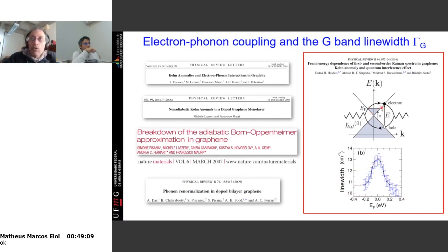Why? Because when you dope the material, you take this level and put it up here. But if you fill the electronic structure up to here, you cannot generate this transition anymore, because of the Pauli exclusion principle: you cannot take one electron and put it into a level that is already full. So if you dope the material up here, this level is full. Then you kill this process, and the phonon line width decreases because the phonon lifetime increases.